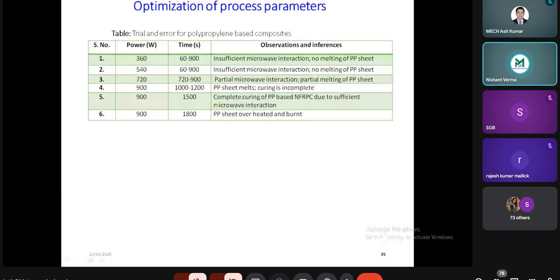So we have optimized the microwave power. Generally, in industrial or domestic microwaves, you can see that there are multiple power levels: 360, 540, 720, 900. And this is how we optimized it. In the case of 360 microwave power, insufficient microwave interaction takes place and there is no melting. Otherwise we could heat for a longer time, but that is not feasible.